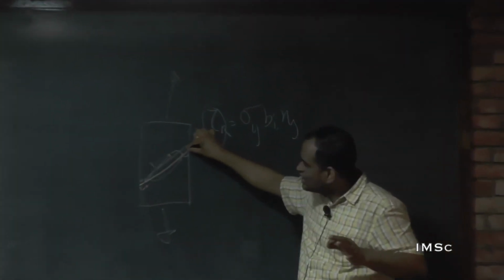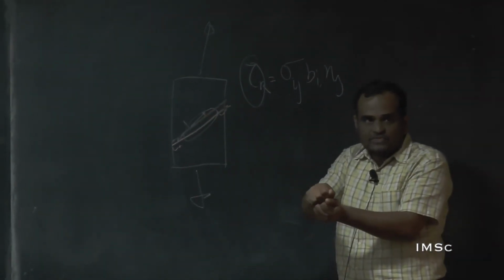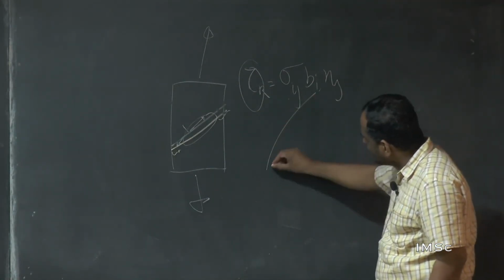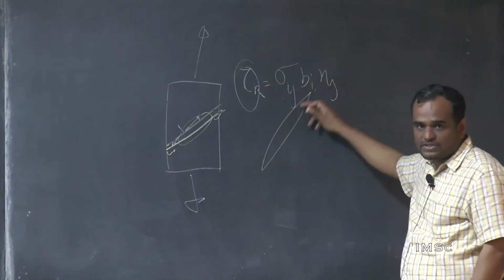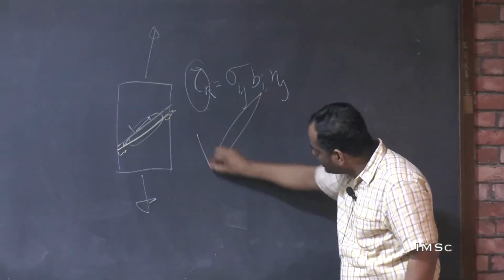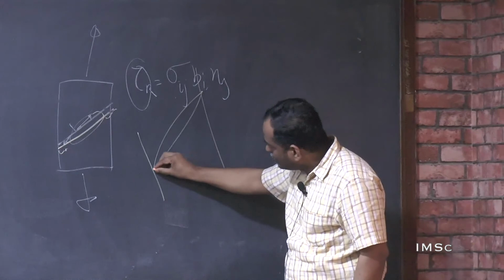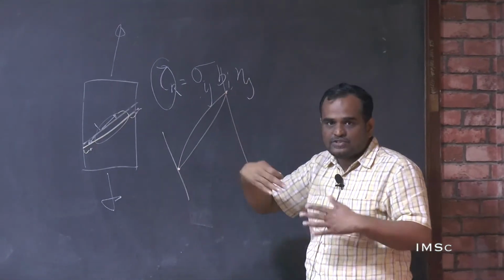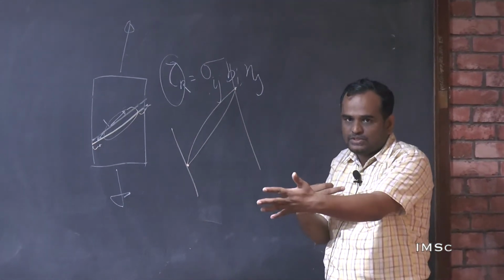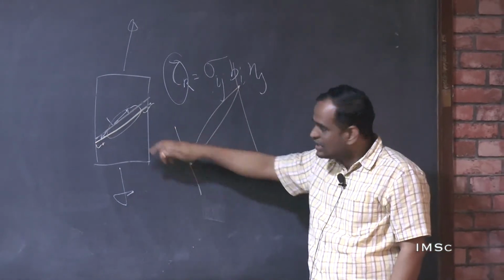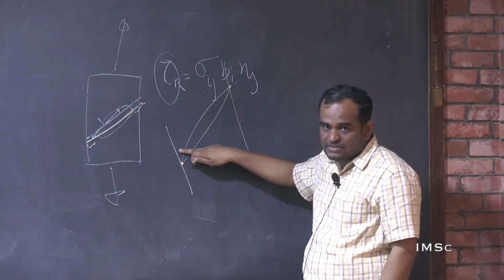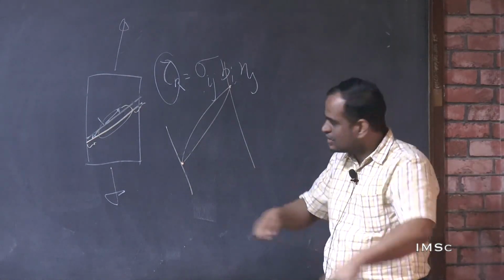The twin is locked in, because only the center part is favorable for it to grow. As a consequence, you start seeing these lenticular structures, because wherever there is a boundary, the twin sees a negative resolved shear stress that does not allow it to move further, but away from it you see a positive resolved shear stress. To overcome this, you need to apply a lot more stress.